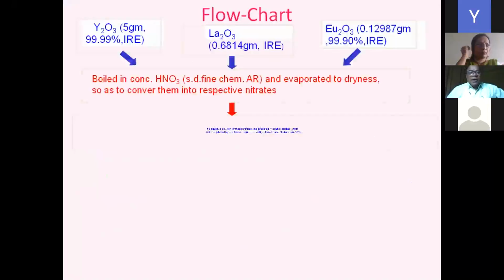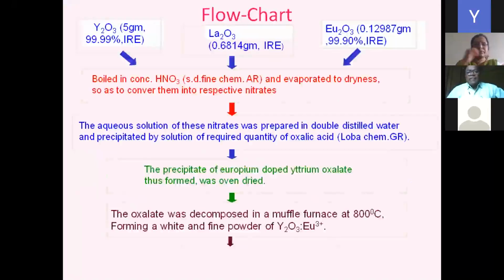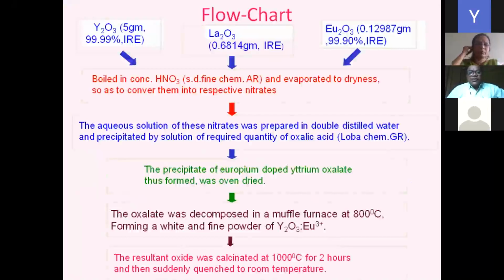The same thing, boiling in concentrated nitric acid. The ingredients are added. The aqueous solution of these nitrates was prepared using deionized water and precipitated by the solution required from oxalic acid. The precipitate of europium doped yttrium oxalate is formed, was dried, and then the oxalate was decomposed, and a fine powder of the oxide formed. The resultant oxide was calcined at 1000 degrees centigrade, and then suddenly quenched to room temperature.